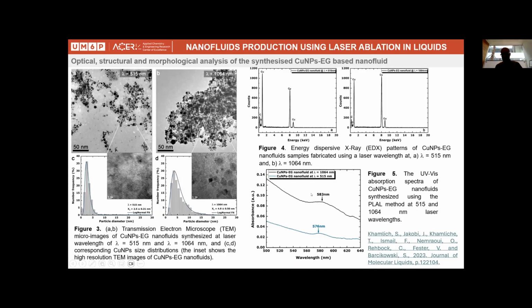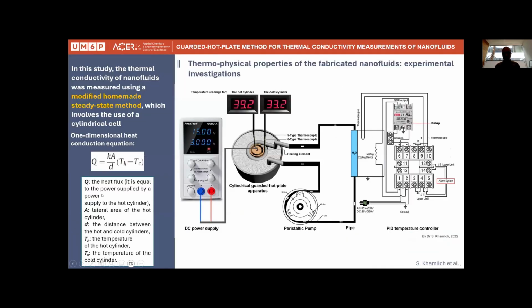Of course, we have done some optical analysis. Copper has a surface plasmon resonance, which means it absorbs light around the visible region and shows clearly, compared to the literature, that these are nanoparticles of copper. Particle size distribution-wise, the particles are really below 10 nanometers using different wavelengths of lasers. Of course, the green light of the laser gives us an even narrower particle size, which is really beautiful there. Of course, producing this nanofluid. Sorry, colleagues, I'm speaking fast because of the time, but I'm going to make sure that we finish this in time.